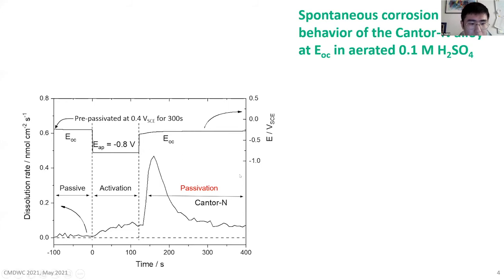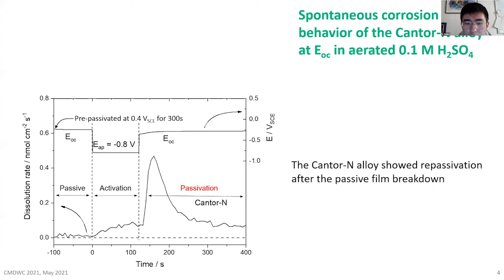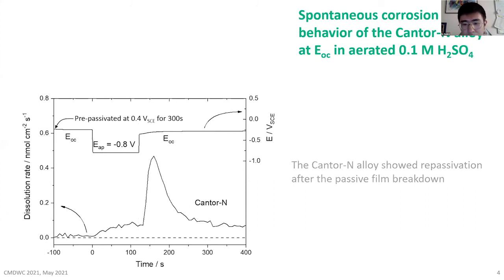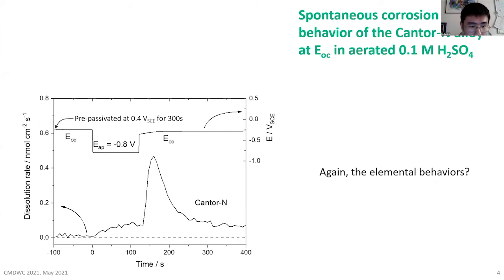After the passive film breakdown, we observed a dissolution peak, and following the peak, the dissolution reduced to a very low value. So this implies that the Cantor N alloy showed repassivation behavior after the passive film breakdown. Again, what are the elemental behaviors during this experiment? They are shown in the figure.